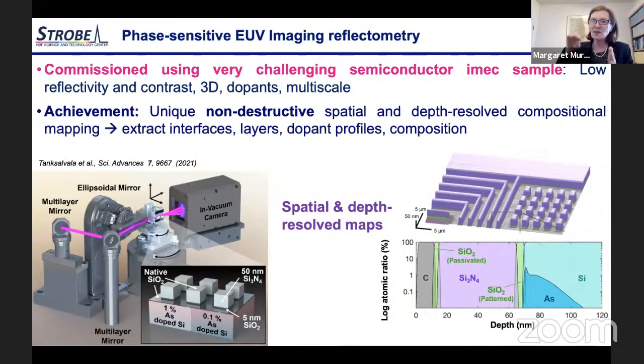AFM is great. It gives us the height very well, but it doesn't tell you what is in the material. And of course, electron microscopy is great, but the statistics maybe are not good enough to be able to really extract the dopant profiles. So in these maps, these colors designate these same materials underneath the sample.